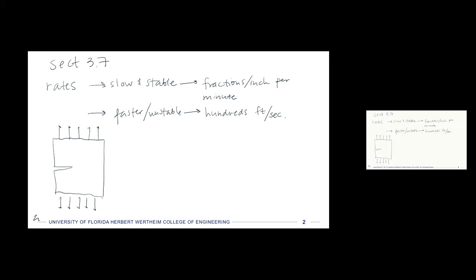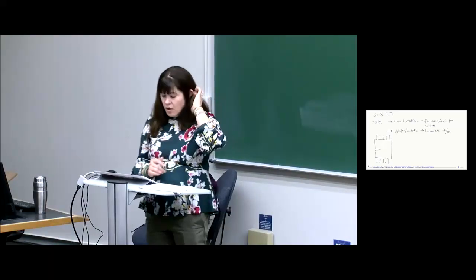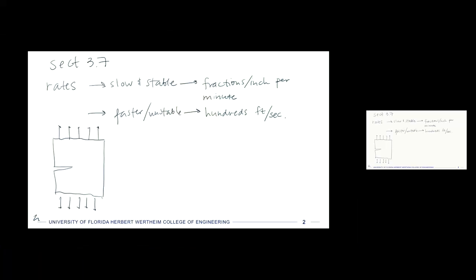If this was a tensile test and we were trying to measure modulus and yield strength and things like that, it would not have a notch, and we would assume that stress is applied throughout the entire cross section. When there is a crack, the first thing you can immediately see is that if we look at a cross section right through where that initial crack is, the area through which that force goes is much smaller, depending on how big the crack is. And so our nominal stress is higher now. When we apply stress concentration factors for these kinds of problems and say something about the nominal stress, that would be the cross-sectional area minus where that crack is, so it does not include that. The nominal area is lower.